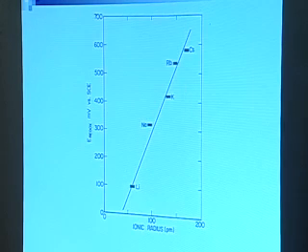Before you do that, if you simply plot the redox potential of the iron system as a function of the ionic radius of the various cations, you see this wonderful linear relationship, which to us suggested that something happening here was a solid state phenomenon. However, there is another interpretation, and that is that if you plotted this instead against hydrated radius, then you'll get a straight line going in the other direction.